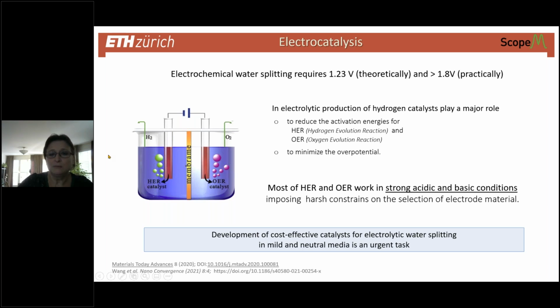Now, usually these reactions run in strongly acidic or basic conditions, which in turn impose very hard constraints on the selection of electrode material. So the main motivation for a lot of groups is to design catalysts that enhance or promote the kinetic rate of the reaction, especially the oxygen evolution reaction, in neutral or mild media. This is where our story starts.